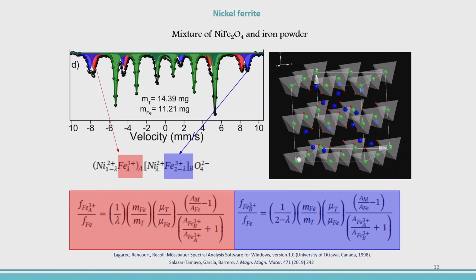But we have to take two important things into consideration. First, this mass here is not just any mass. This mass is between the range of two masses: the ideal mass that is derived from the ideal thickness, taking into account the area of the sample holder, because you can change the sample and then use another value. But you have to be careful that you are below the ideal thickness, and above the mass that, of course, is zero, the mass that does not produce thickness effects. This is the first thing. So the mass has to be in this range.